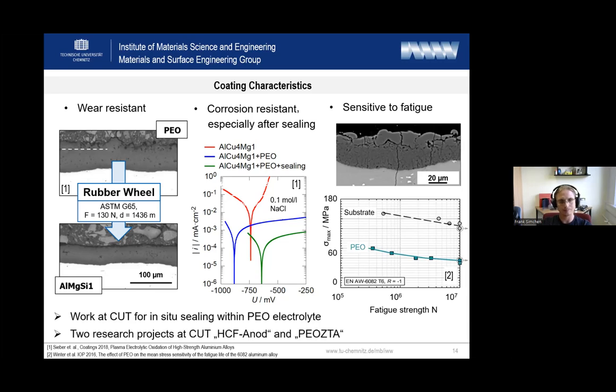And yeah, regarding the sealing, I want to say that we are working in our working group on a process to apply an in situ sealing step within the PEO electrolyte. So we create a PEO coating, and after this the component stays inside the electrolyte and we change the alternating electrical regime, play with some pH shifts which occur there, and then we apply the sealing in situ. So after you take the component out of the bath, you have your formed PEO coating, and you also got your sealing, which closed the remaining pores.